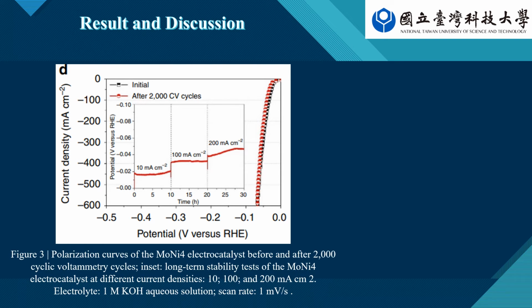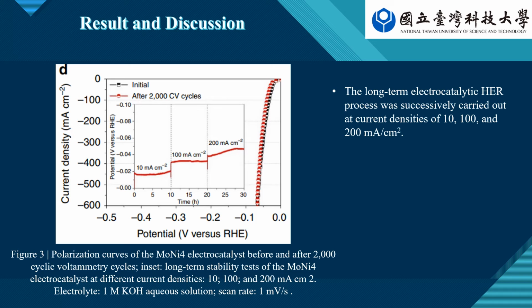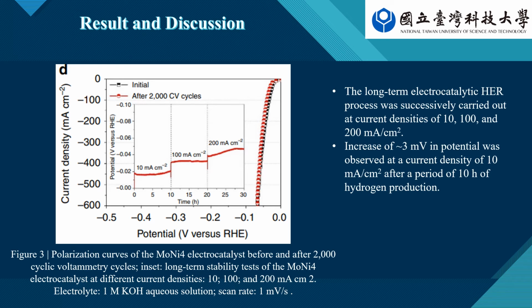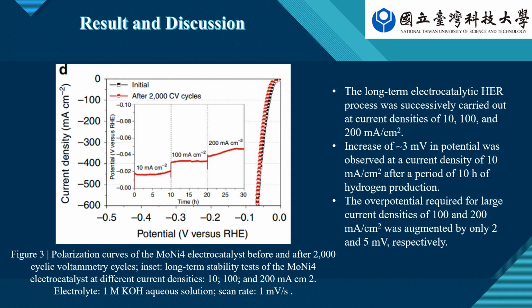Long-term electrocatalytic stability is another important criterion for HER electrocatalysts. In addition, a long-term electrocatalytic HER process was successfully carried out at current densities of 10, 100, and 200 milliampere per centimeter squared. The inset in figure 3D demonstrates that the MoNi4 electrocatalyst retains a steady HER activity, and only an increase of around 3 millivolts in potential was observed at a current density of 10 milliampere per centimeter squared after a period of 10 hours of hydrogen production. The overpotential required for large current densities of 100 and 200 milliampere per centimeter squared was augmented by only 2 and 5 millivolts respectively.